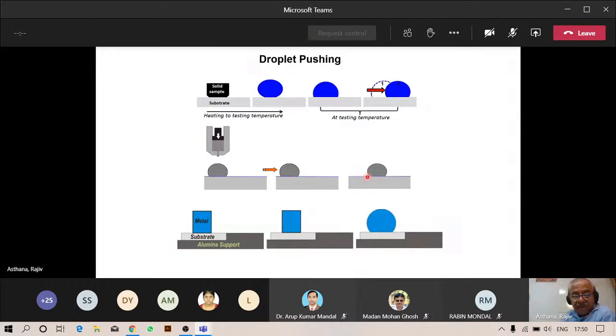We also did this kind of a thing where we had contact heating on one type of substrate, for example, magnesium oxide and nickel here. And then after melting, we could actually slide the droplet from one substrate to another substrate. A lot of these things are possible because of sophisticated instrumentation and very controlled conditions. So here you're looking at pushing of the droplet.